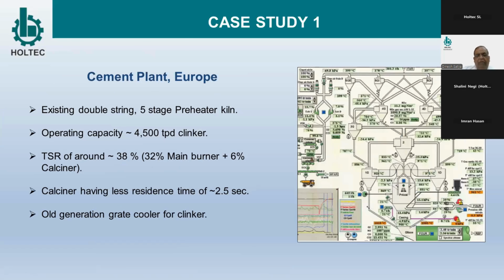Now we come to the case study. Recently, we completed a cement plant upgradation or modification at one of the plants in Europe. The existing plant was a 5-stage preheater plant with a capacity of 4,500. TSR was already running at 38%, which was majorly fed into the main burner. Calciner was 6%. The main reason is the calciner size; residence time was very small, 2.5 seconds, so they were not able to push more in the calciner. Further, the coolers were also old generation coolers, so there was a lot of possibility for modification to improve heat consumption in the cooler.